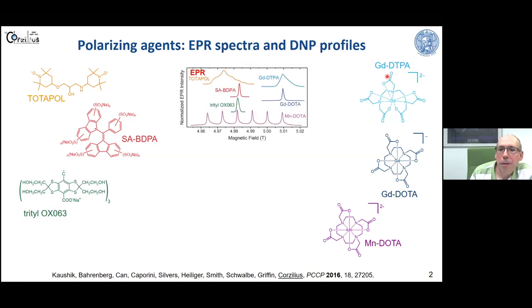If we compare the EPR spectra of those, they differ in some respects, but they're also very similar. They are similar because they all occur in a rather narrow magnetic field range. So these are all paramagnetic species which have an EPR resonance close to that of the free electron. That is an important factor, and I will introduce today why that is and in which cases this might deviate, or which metal ions we can use and which might not work.